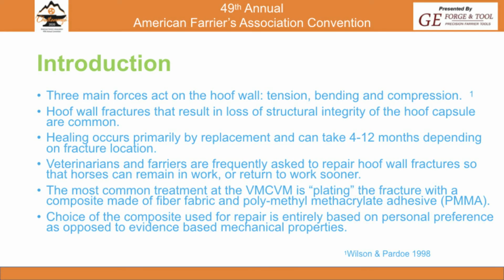And again, the hoof wall fractures or cracks result in the loss of structural integrity within the hoof capsule. Obviously, they only heal by replacement by growth. They only heal from top to bottom. They don't just all of a sudden start growing in and out. But obviously, you guys know that. And frequently, we as vets, farriers, practitioners, when we're faced with these, oftentimes we have to find some way to stabilize them for the horses to keep going. Okay? And then again, the most common treatment for us is a plating technique with one of those composites saturated